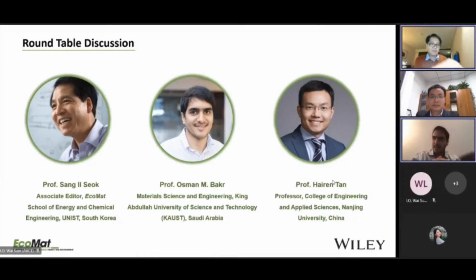So we think we're not that far already, but I think the bigger problem we have with single crystals at the moment is the interface. The VOC is a bit smaller than we'd like, and I think the reason is that because we grow these crystals from solution, leftover liquid from the solution can damage the interface slightly. So this is the biggest problem we have, and so we think the biggest room for improvement is getting the VOC to go up.